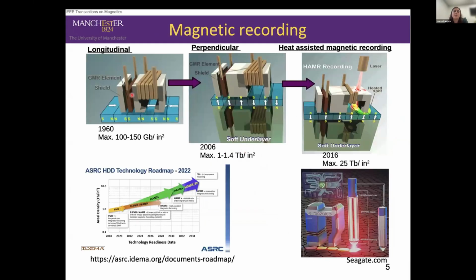So over the years, we have moved from longitudinal to perpendicular recording, and now we are in the era of heat-assisted magnetic recording, where we use materials with a very large anisotropy, such as iron platinum, and a laser pulse to heat up the system and allow writing the information at accessible fields. And currently, this technology exists in the form of the Mosaic hard disk drive developed by Seagate. However, it took about 20 years to get from the concept of heat-assisted magnetic recording to the device level.